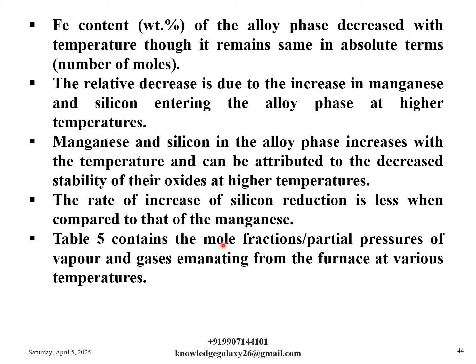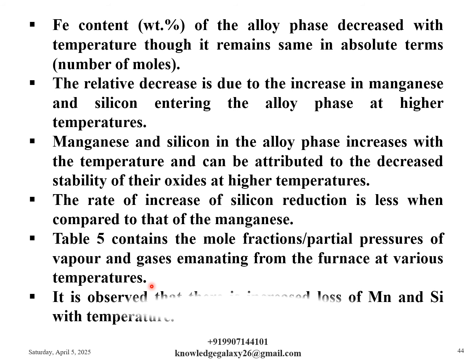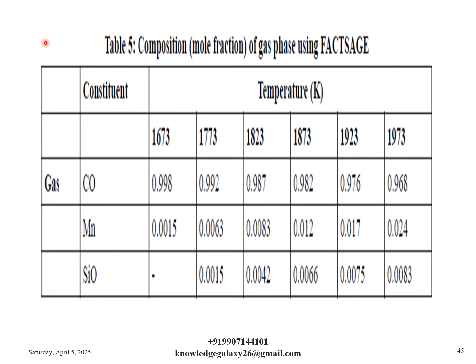Table 5 contains the mole fractions or partial pressures of vapor and gases emanating from the furnace at various temperatures. It is observed that there is increased loss of manganese and silicon with temperature. So this is table 5, which shows the composition in mole fractions of the gas phase in FactSage.